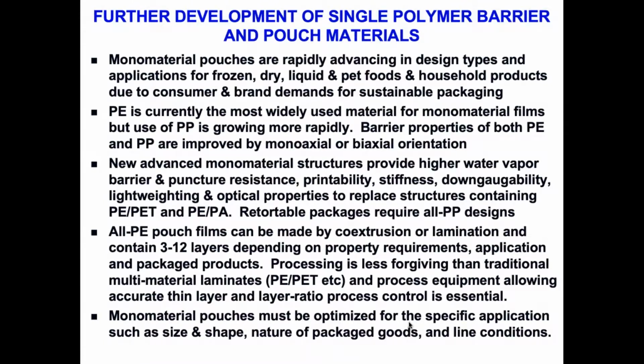This monomaterials technology is now being developed considerably further, and the pouch structures are rapidly advancing in design types and applications for a whole range of products. PE is the most widely used material so far. Polypropylene is growing rapidly. The barrier properties of both of these are improved by orientation. And these new advanced monomaterial structures provide high water vapor barrier, high puncture resistance, printability, stiffness, down gaugeability, lightweighting and optical properties. So they can replace structures containing PE multi-layers or PE/PA. And there are now also retortable packages which require all polypropylene designs.